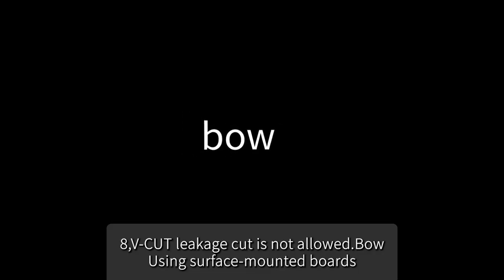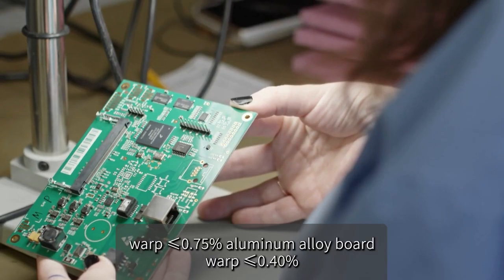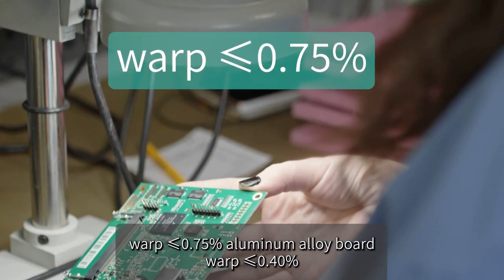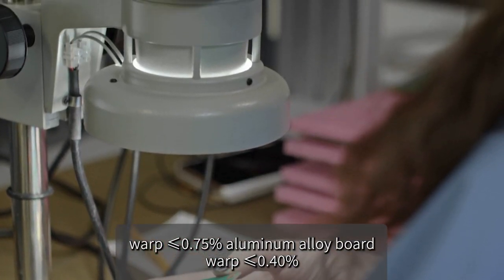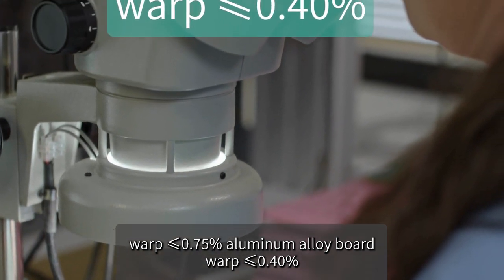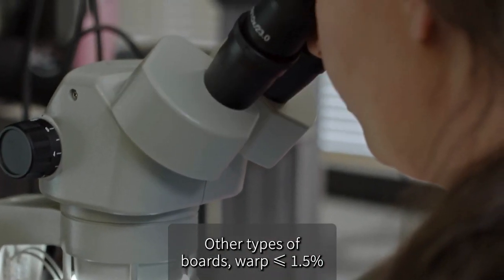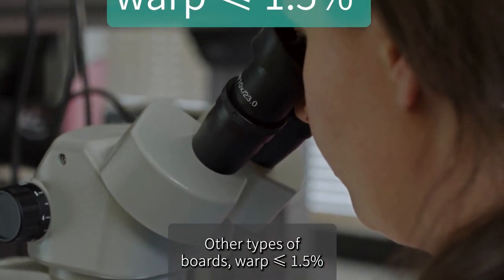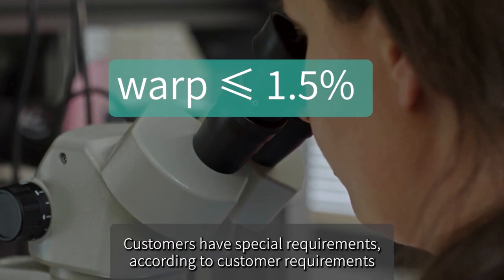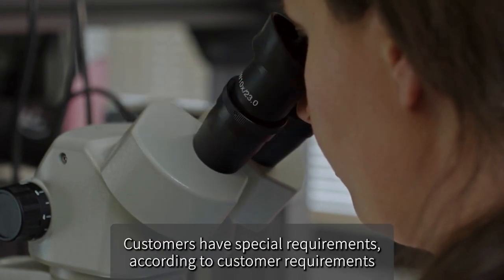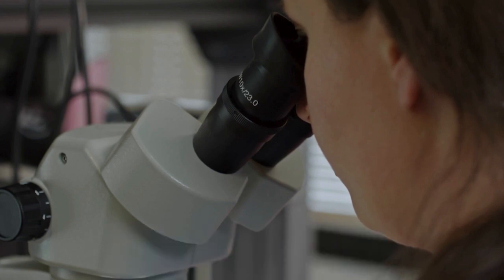Bow. Using surface-mounted boards, warp less than or equal to 0.75%. Aluminum alloy board, warp less than or equal to 0.4%. Other types of boards, warp less than or equal to 1.5%. Customers have special requirements, according to customer requirements.